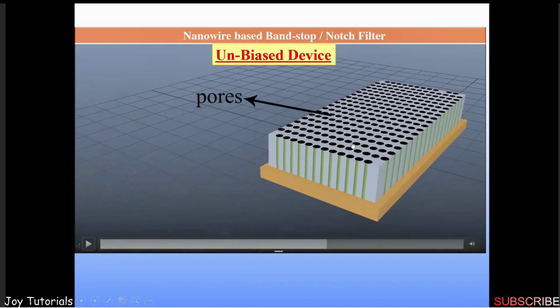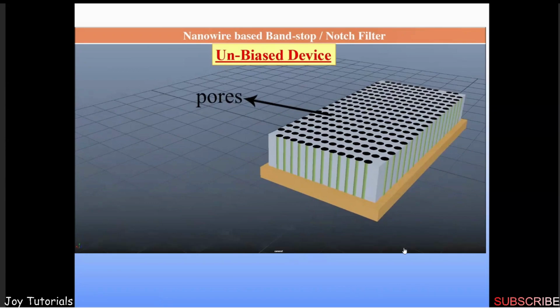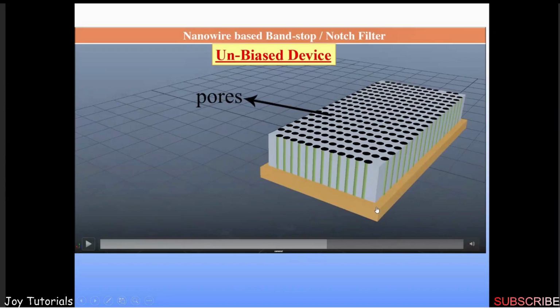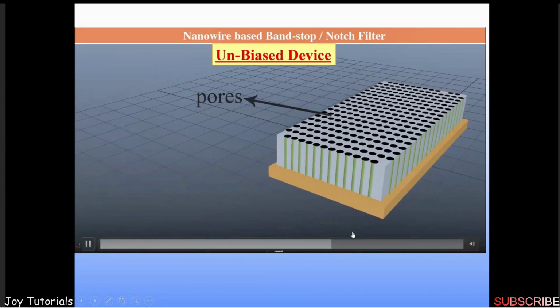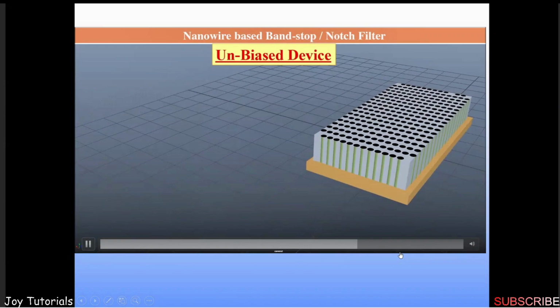What we have is, in the nanowire, we buy the templates commercially available. Then we deposit a metallic layer at the bottom of this. So this acts as a metallic layer for the deposition of the magnetic metal layers through the 3 electrode system.